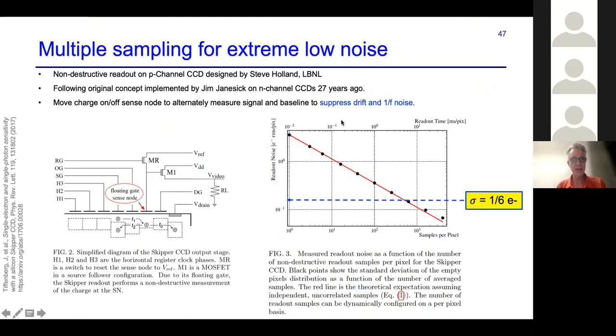And that idea was to overcome the limit in the reduction in noise that comes when you integrate. You can see this curve, we're showing integration time, and the curve flattens, and it reaches a floor due to 1/f noise in the buffer transistor, which is insurmountable, except if you can move the charge noiselessly off the sensing node, re-establish the baseline, remeasure the baseline, and then put it back on again. And so the charge skips on and off the sense node. It's called a skipper CCD. And after many, many cycles, you actually can continue to beat the noise down. So you only have to integrate away the white noise because you're actually subtracting the baseline drift out. And you're subtracting the 1/f noise.